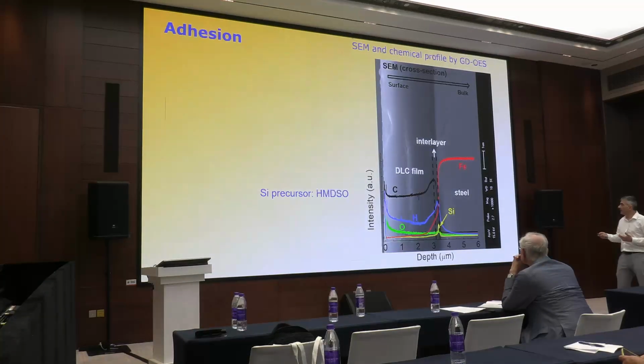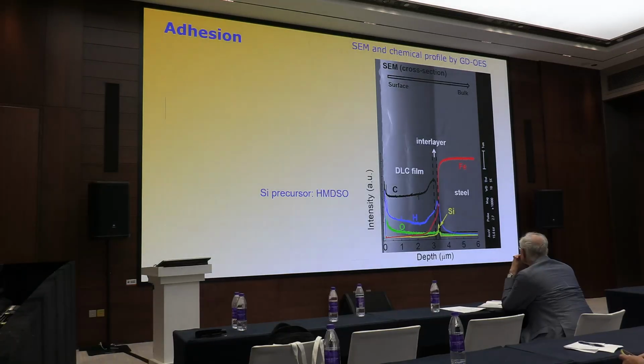Here you can see the material system. This is a cross section. This is the steel, this is the GDOES characterization. You can see the iron from the steel. This is the interlayer made of silicon, carbon, and obviously hydrogen. And this is the DLC film, the hydrogenated amorphous carbon thin film.